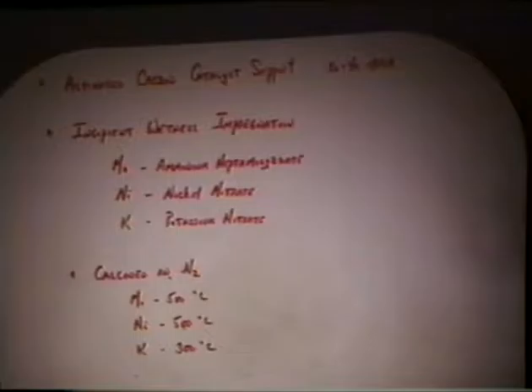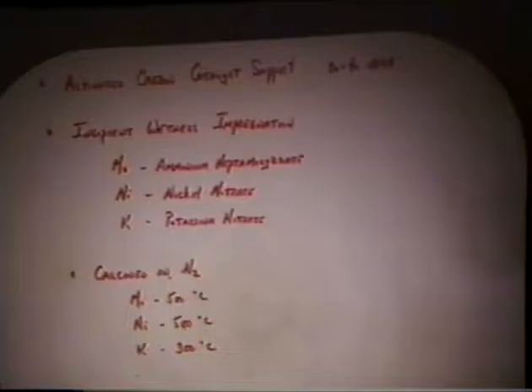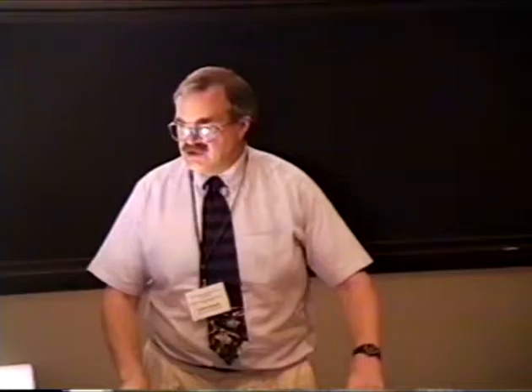The materials that we're working with are carbon-supported molybdenum catalysts. The moly is added by incipient wetness with ammonium heptamolybdate. Nickel is added as nickel nitrate, and potassium as potassium nitrate. What's commonly done if you're adding multiple components in multiple steps is that you will calcine after adding each material. The difficulty with carbon-supported catalysts is if you calcined it, it burns and disappears. So we introduced a high-temperature step in nitrogen using carbon at 500 degrees C in order to decompose one component at a time before we continue to add additional components.